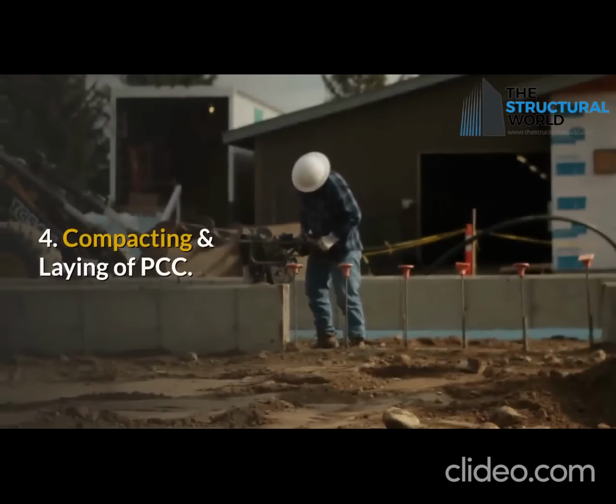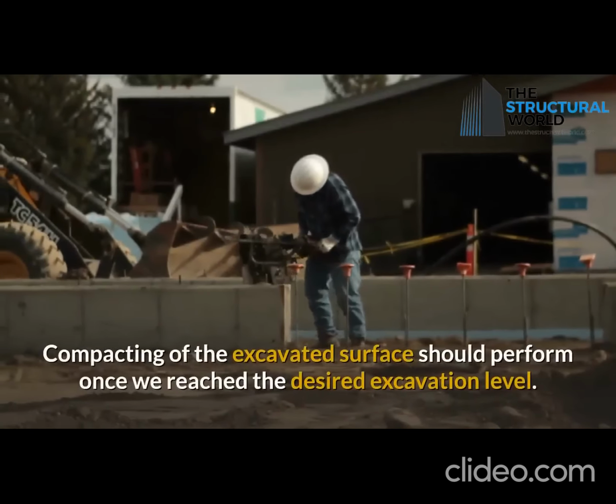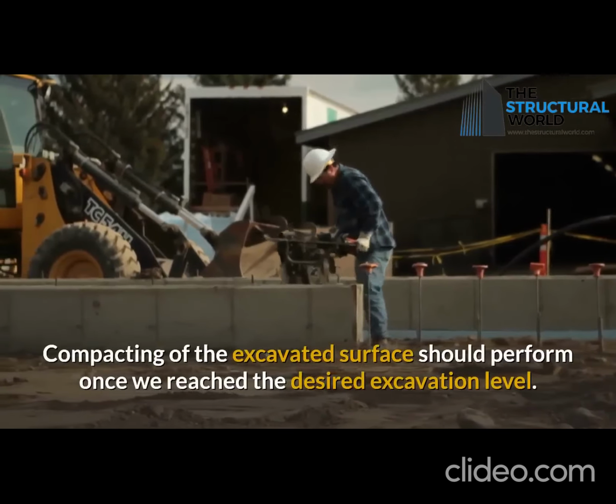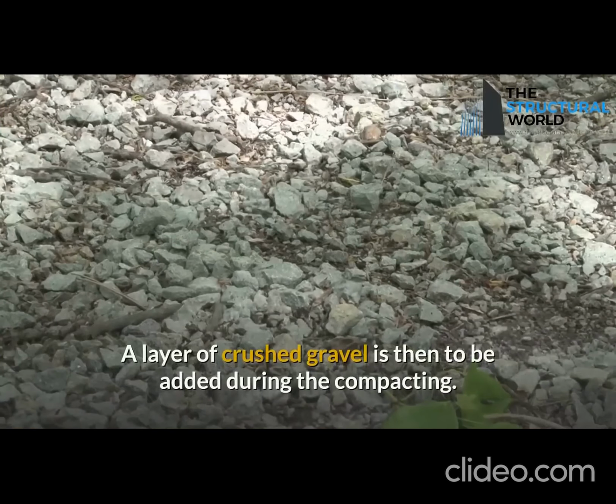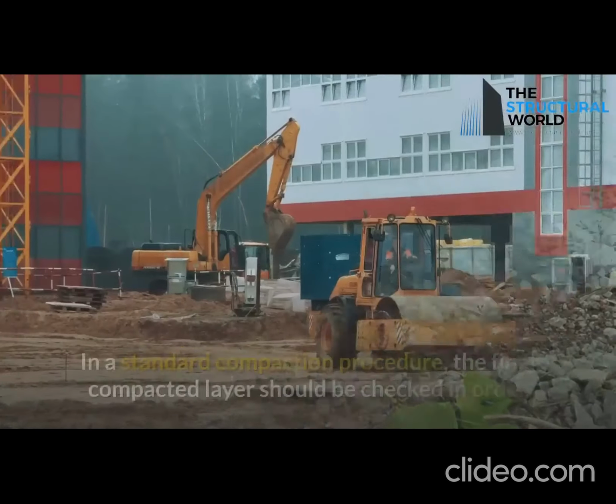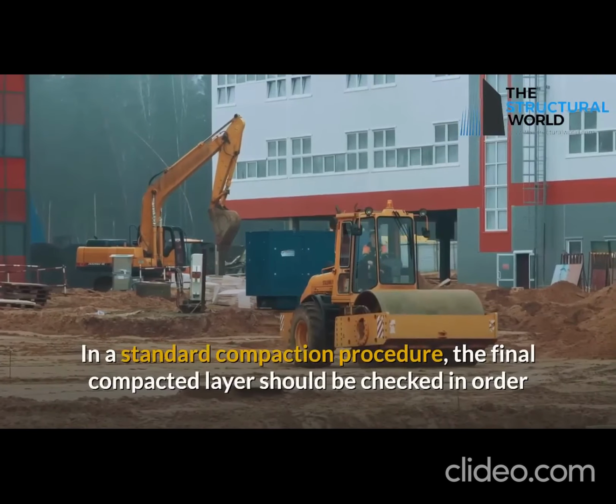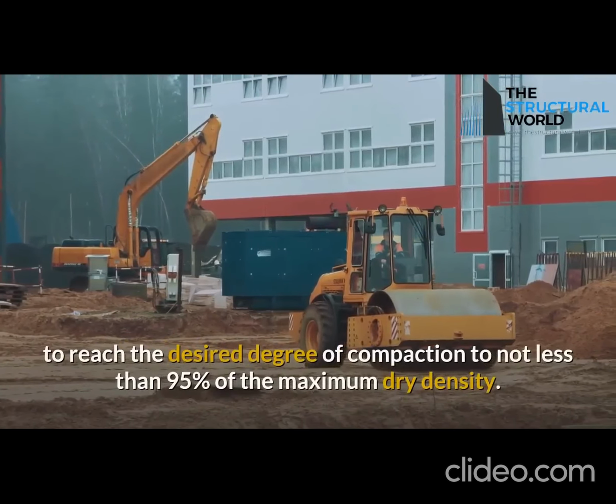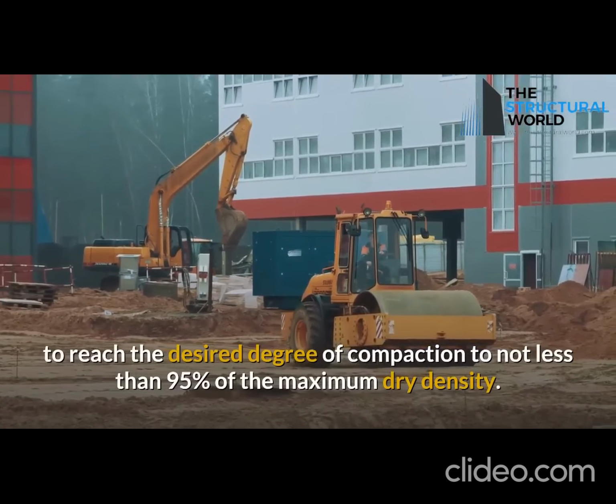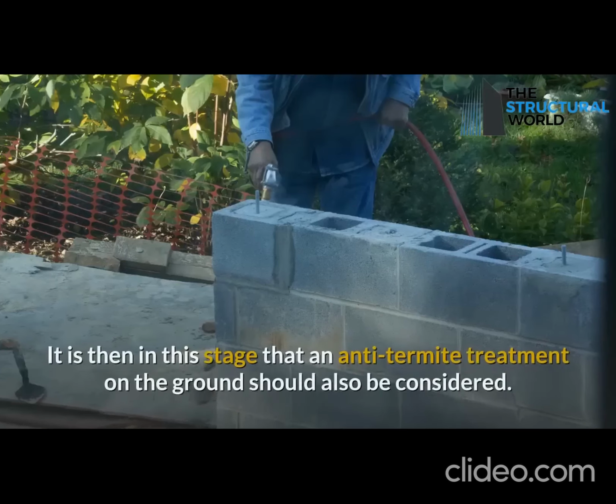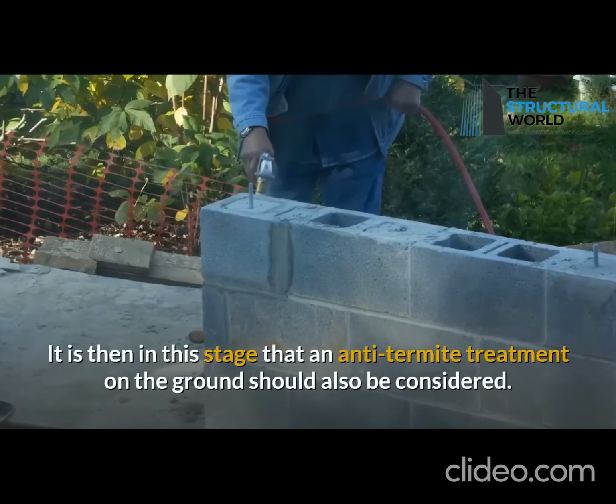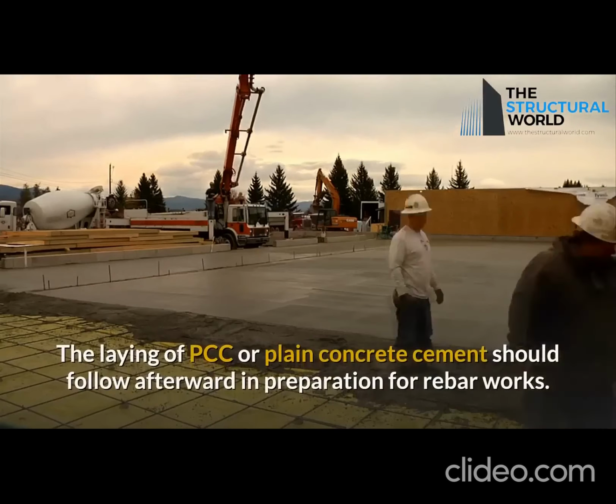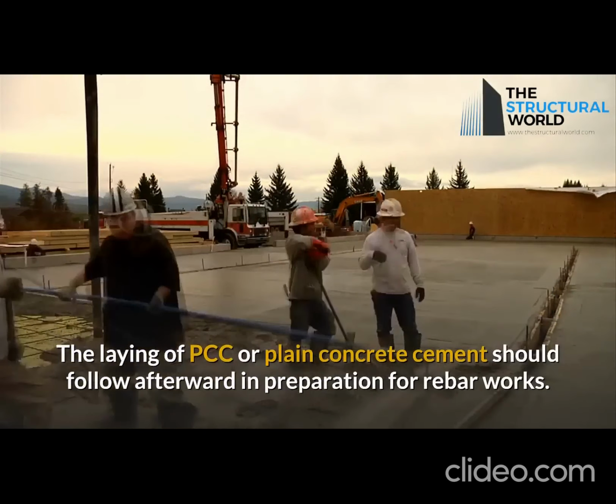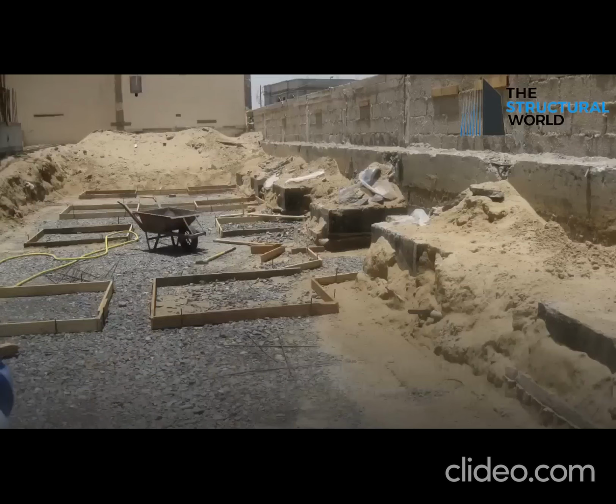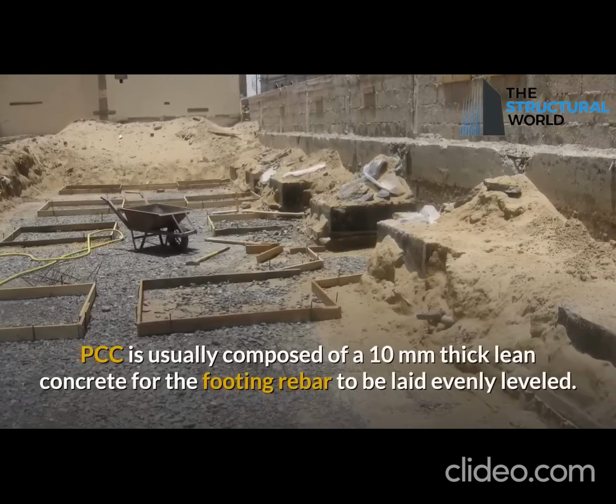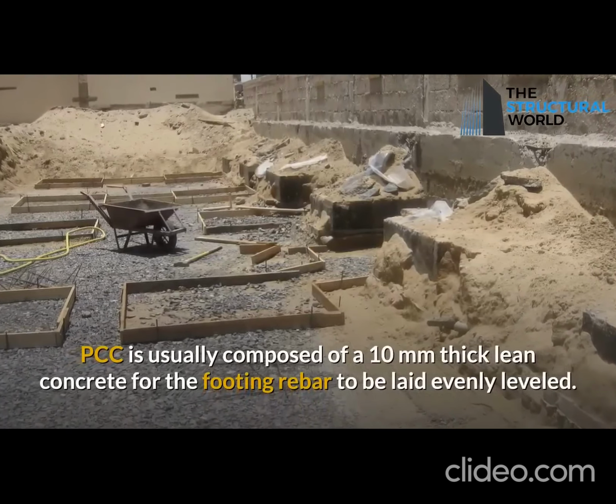4. Compacting and laying of PCC. Compacting of the excavated surface should be performed once we reach the desired excavation level. A layer of crushed gravel is then to be added during the compacting. In a standard compaction procedure, the final compacted layer should be checked to reach a degree of compaction of not less than 95% of the maximum dry density. It is in this stage that an anti-termite treatment on the ground should also be considered. The laying of PCC or plain cement concrete should follow afterward in preparation for rebar works. PCC is usually composed of a 10 mm thick lean concrete for the footing rebar to be laid evenly leveled.